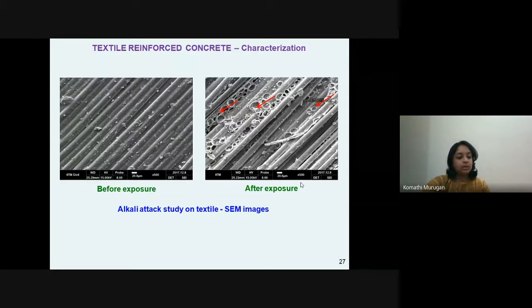Now we will move on to the durability characterization of this textile reinforced concrete. The pictures here show the alkali attack study on textile, the scanning electron microscopy images. The first image shows a textile which is zoomed in and taken in the scanning electron microscope. So this is the surface of the fibers. These are the filaments, essentially the fibers, which are not attacked by alkali, that is, this is before exposure.